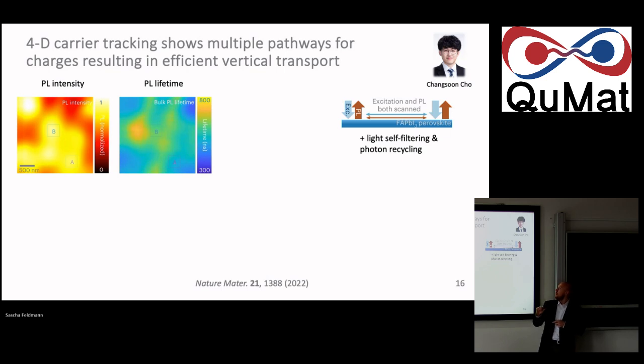What we now also do is that we don't just scan away from excitation, but we also look at the luminescence from both sides of the film. So we don't just excite from this side and then collect from this side, but we can also excite from the top side, but collect luminescence from the bottom side. And again, this luminescence spectrum will be looking different. It will be probably redshifted because all this light must have now traveled through a lot of the bulk material.